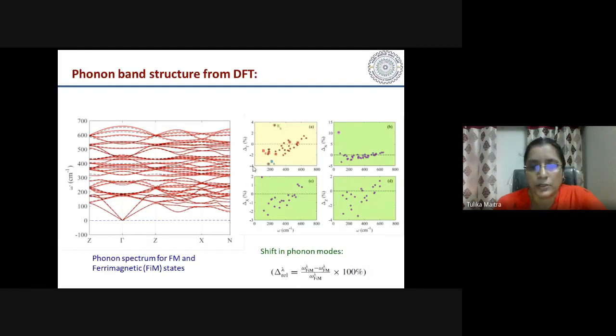Okay. So which we have plotted here, and we see that this is one mode which is softening with the change in magnetic state, whereas this mode is hardening with the change in the magnetic state. So this mode is at the zone center, at the gamma point, and this is at N, which is the zone boundary. Okay. So the different modes are affected differently by this change in the magnetic state.